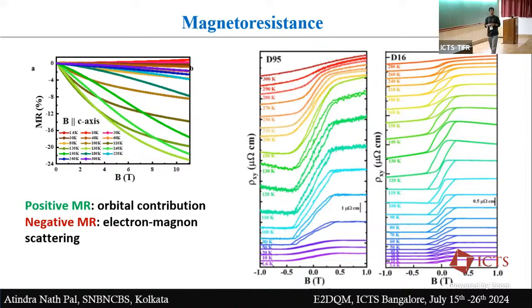Actually, that's the question the referee asked. In the 2D limit, that's why you are seeing the hysteresis. This is already there in bulk, and hysteresis is more prominent in the 2D case. You are going to the hard ferromagnetic regime. Another thing is that in Raman spectroscopy, we see a different signature in the thin layer compared to the bulk. So it's not pure bulk.